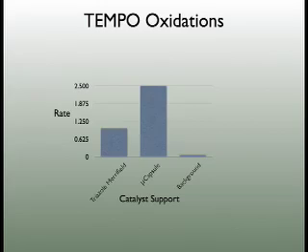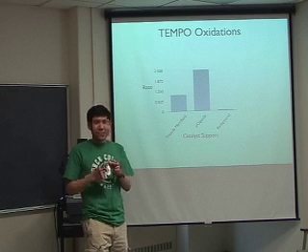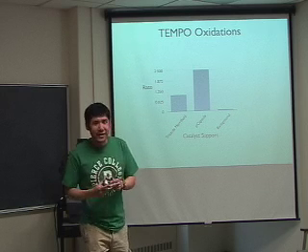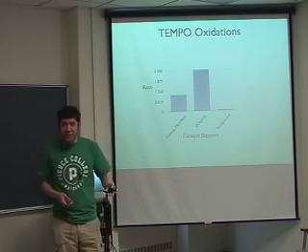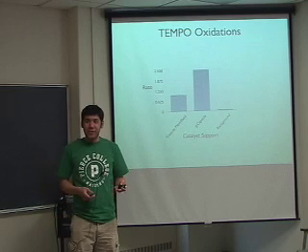Turns out that we get a nicer rate of reaction for a lot of these catalysts than we would on some other solid support. So in addition to controlling the microenvironment, we can also sort of control rate. We can make the shell either thicker or thinner based on how fast we want the catalyst to go. And so now we have a suite of catalysts where we can begin to think about multi-step reactions in the same pot.